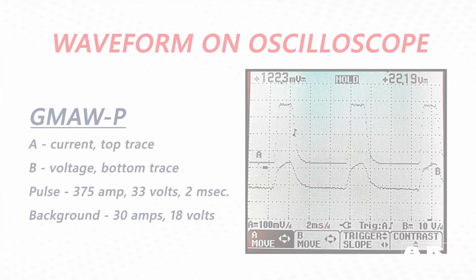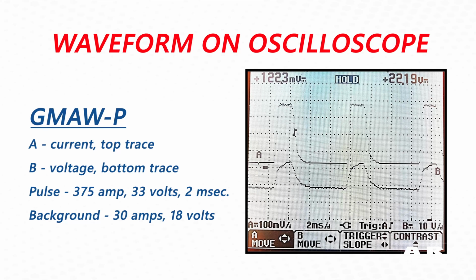And so let's kind of shift gears now and look at gas metal arc pulse welding. Here we see a picture of the waveform of a pulse weld. The top trace is the welding current, and the bottom trace is the welding voltage. And if you look at it closely, you can see that the pulse time is just under about 2 milliseconds, and the peak current is 375 amps at 33 volts, with the background current of only 30 amps at 18 volts.